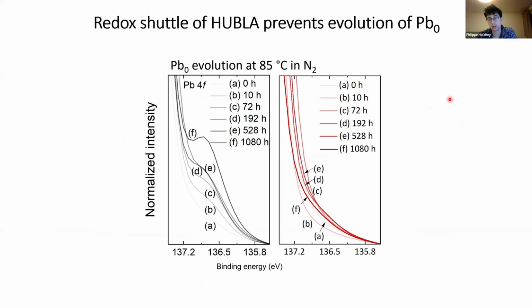So one proof for this is with XPS. So we looked at this lead zero evolution over time at 85-degree aging. So we aged some films over 1,000 hours at 85 degrees and measured XPS continuously on those films at 85 degrees. And you can nicely see how over time the lead zero shoulder is forming for the films without the HUBLA. And for the films with the HUBLA, we don't see any shoulder forming. So that's for us a strong signal that the thiocarbamate bond is indeed working as a redox shuttle.